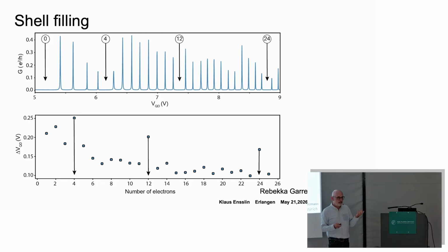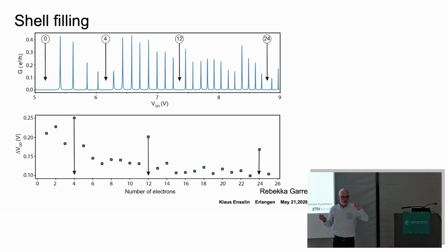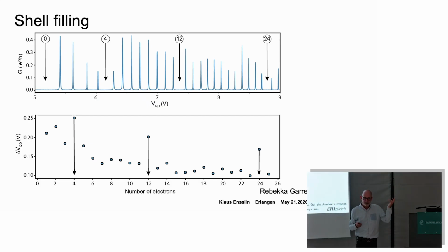So I think it's very suggestive that because of this very simple geometric assessment in real space that we started out with, you can directly see that in the shell filling of a graphene quantum dot. So that's the S state, filled by 4 electrons because you have degeneracy of spin and degeneracy of valley. Now let's move on. Electron 4 to 12, the next 8 electrons. Well, what's happening? The next orbital state is a p state. The p state in 2 dimensions is twofold degenerate. So you have 2 for p, 2 for valley, 2 for spin. That's 2 to the power of 3. That gives you 8. That means filling in 8 electrons here. So we understand this one.